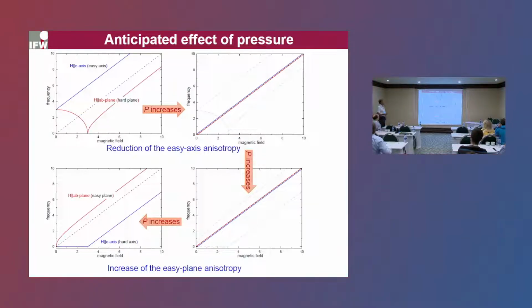One possibility would be to apply pressure, hydrostatic pressure. In that case, we thought we could see it by changing the properties of the ferromagnetic resonance. In the absence of pressure, we have these two excitation modes, which have different energies due to the magnetic anisotropy. If, for instance, we increase the pressure, it might happen that the anisotropy gets smaller, and therefore these modes would merge into a single line, and eventually we possibly could even turn the type of the magnetic anisotropy from easy axis to easy plane. And indeed, it was realized in our experiment.